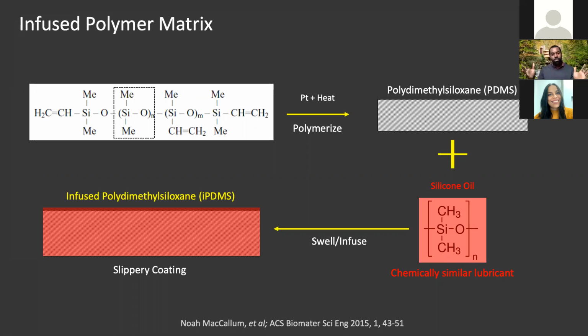There is this dimensional change that happens. But at the end of that dimensional change, there is a lubricant layer that is presented at the surface. And the benefit of this approach is if that top lubricant layer is lost, you have this reservoir in the polymer matrix that will then continue to replenish as there is loss. So this is all kind of thermodynamic design. We're trying to figure out how can we get the lubricant to be stable on the top surface? This is pretty interesting, and there's a lot of interesting physics that goes into this. That's still kind of evolving, of trying to do this with not just PDMS, which is great for some medical systems, but other materials as well, to just have, let's say, this 2D slippery coating rather than this nano-textured or structured coating.